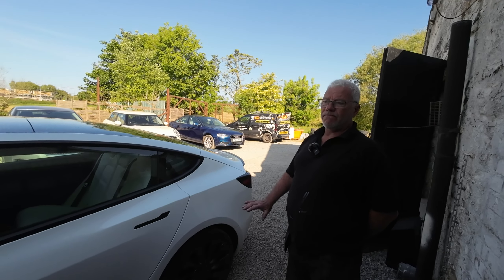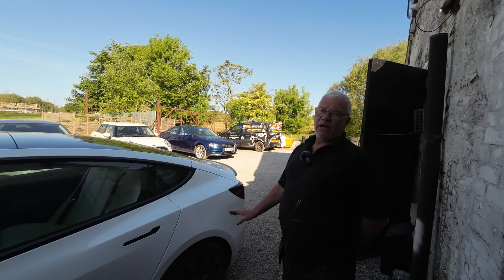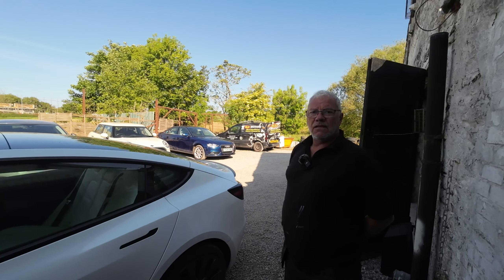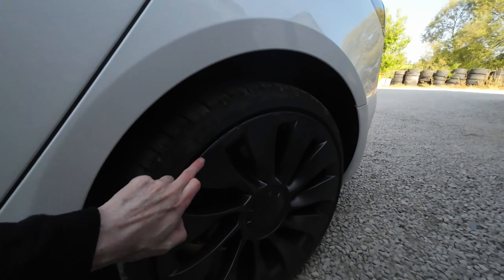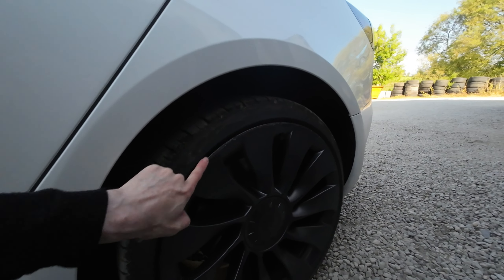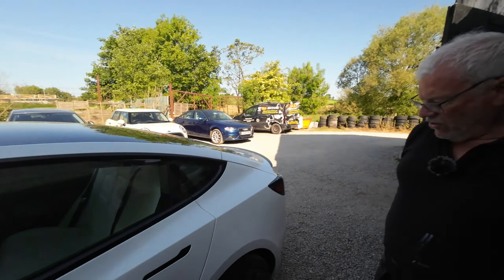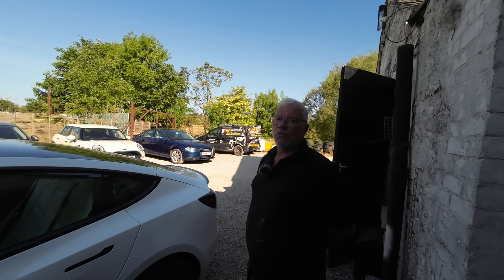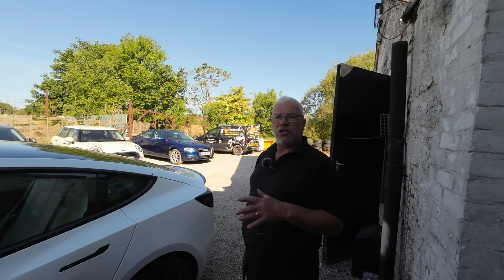And then shot blasted, washed, then powder coat primed, coloured, and then powder coat lacquer. Right, that's brilliant. So in terms of the areas that I've scuffed in here where it's a bit divoted - does that get filled back in or does that just get smoothed out? Basically what we do, if they're too deep, they're TIG welded and then machined. If they're only light, they're just machined. That takes out the grooves and the gouges.